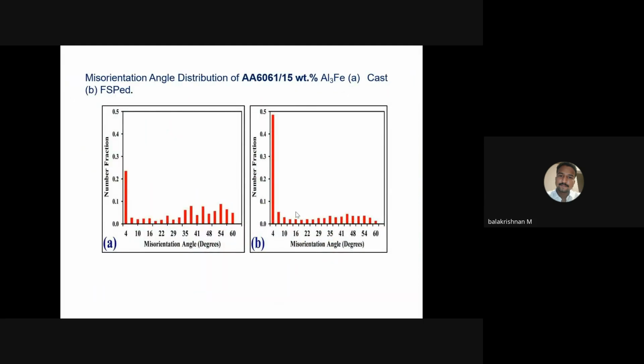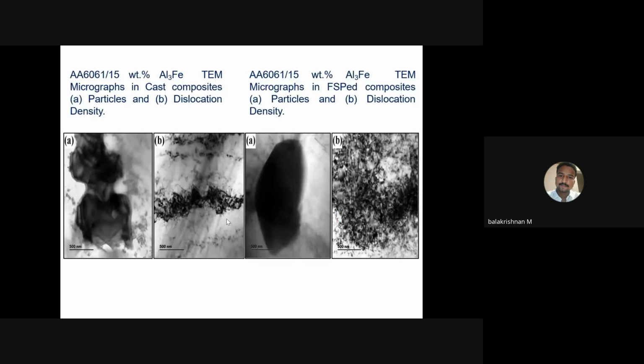Then the misorientation angle distribution, during casting and after FSP. Here we can see that the angle distribution is totally very low compared to the casted matrix.